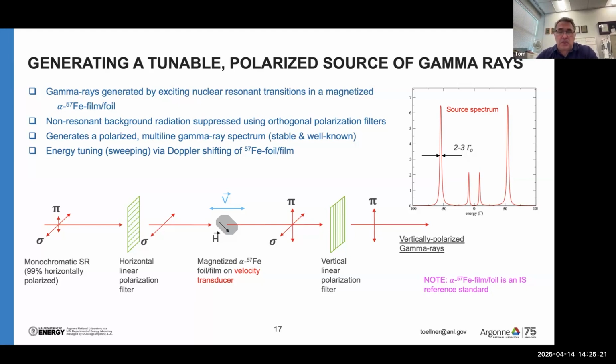The beam excites the nuclear resonances in a magnetized alpha iron film, and this film is mounted on a Mössbauer velocity drive. After the film, there's a 6-line spectrum, a combination of left circular, right circular, and linearly polarized radiation. And then it goes to a vertical linear polarization filter that gets rid of any sigma polarization that comes from delta m equals 0 transitions. And then we're left with just a pure polarized beam that has the 4-line spectrum that you see there. You see lines 2 and 5 of the standard 6-line Mössbauer spectrum are missing, but this 4-line spectrum will be the source spectrum that we will use.